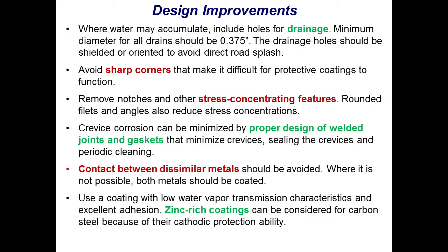And then stress concentration, like we mentioned, either in corrosion fatigue or in SCC, stress corrosion cracking, the mechanical stress is really accelerating the corrosion. So if we could relax the stress, that's better. Now welds, again, it's a big problem. Wherever you have localized features, which is stress concentration or whatnot, or dissimilar metals touching each other, you have a problem. Unfortunately, traditionally, many of the designs are focused on mechanical properties or considerations, or targeting sodium chloride. But now with magnesium chloride, like I presented on Monday, the attack takes a somewhat different form. So some of the designs targeting sodium chloride no longer work well in the new surface environment.